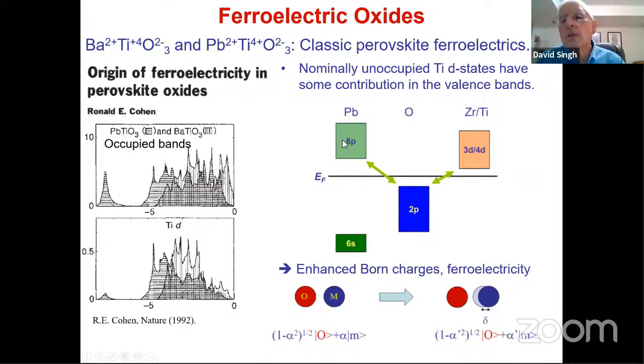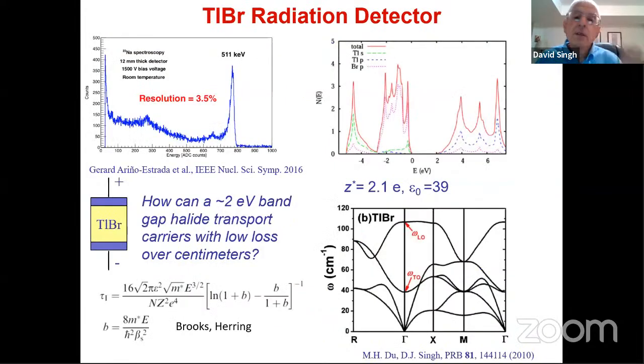And so if you move the atoms, you change the amount of charge that's transferred. And so it looks like you're transferring more charge than just the charge on these atoms. And so the so-called Born effective charge is enhanced and can become quite large in these materials. That's how the ferroelectrics work. And we see the same thing in semiconductors. So some semiconductors, this is thallium bromide, I think I'm not going to go through the details, have a similar feature, and it's related to nearness to ferroelectricity. And the important thing is that kind of chemistry gives very high dielectric constants. And that's very good for the semiconducting behavior of these materials.